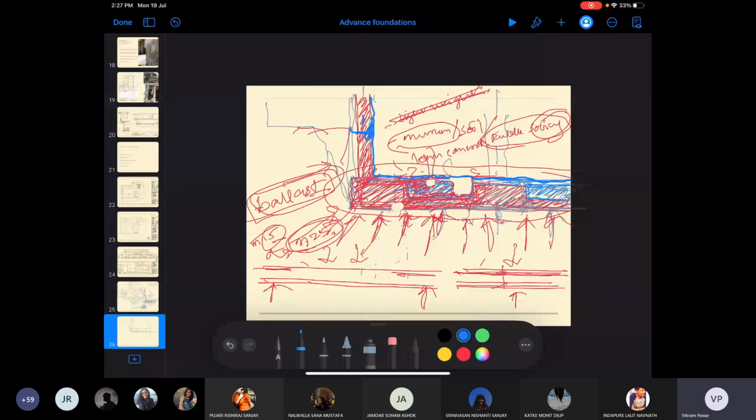Once it accumulates, there is either a vapor pressure or a hydrostatic pressure being built up between the wall and the waterproofing, if it is on the inner side. Because the pressure is being built from the other side, there will be no option but bulging of the waterproofing, and it will start failing. So this inside waterproofing will never survive, given these vulnerabilities.